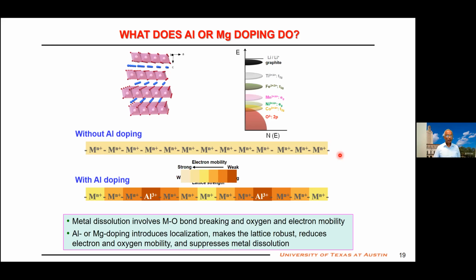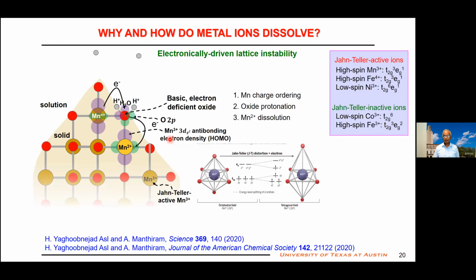All those. As soon as we put aluminum, that acts like a speed breaker. So this electron delocalization is suppressed, a little bit reduced. The lattice becomes more robust. So metal-oxygen bond breaking is suppressed. So dissolution is suppressed. So you get better cycle life. Now, would everything dissolve, all metals? No, not everything will dissolve. Only certain ions. So what is the driving force?